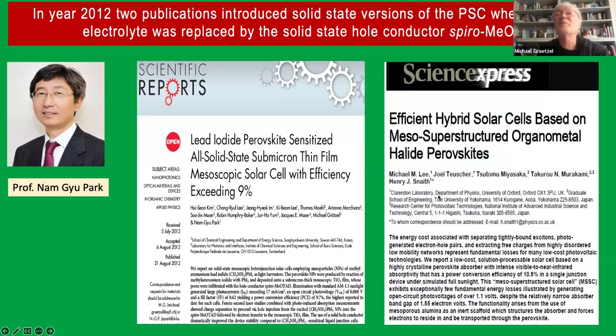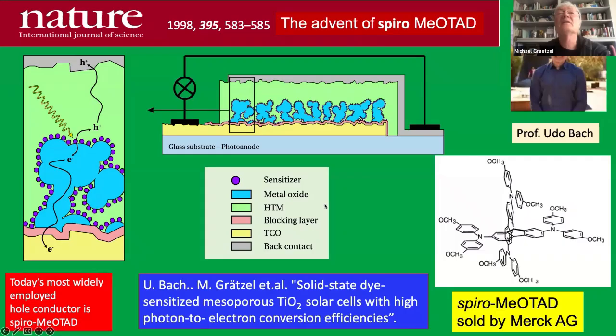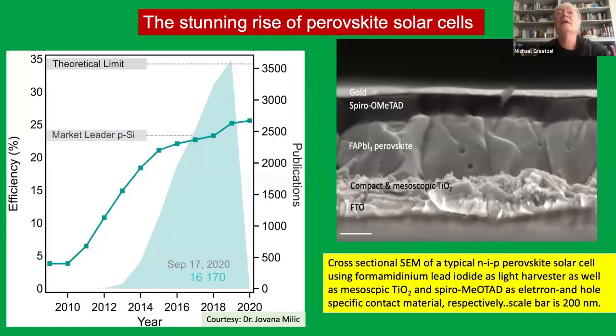And 2 papers appeared, and we're collaborating with Nam-Gyu Park on this pioneer study. And these 2 papers all use the Spiro, the spiro-MeOTAD, that's a triarylamine hole conductor. And that was already published. This molecule was used for solid-state DSCs much earlier, like 14 years earlier. You can see you do fundamental research, and then a decade later, you can use that to your advantage and make a major advance or breakthrough.